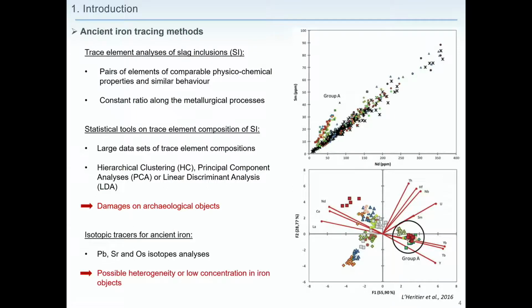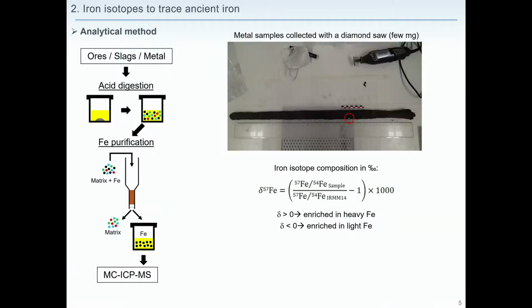In addition, some isotopic tracers have been proposed to trace ancient iron, in particular lead, strontium, and osmium isotopes. Even though promising, this approach may have some limitations, because you can have heterogeneity within the objects. That's in particular the case for lead. And you can also have a very low concentration. That's the case of osmium, which may involve some complicated analytical techniques. So during my PhD, we proposed the use of iron isotopes to try to trace ancient iron.